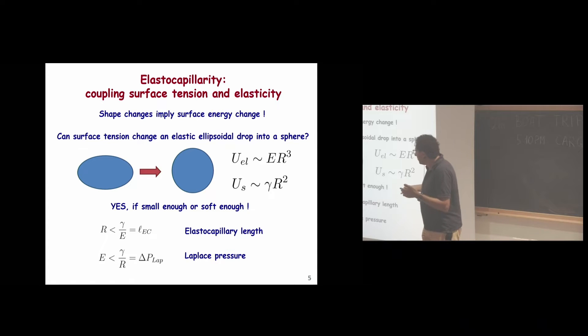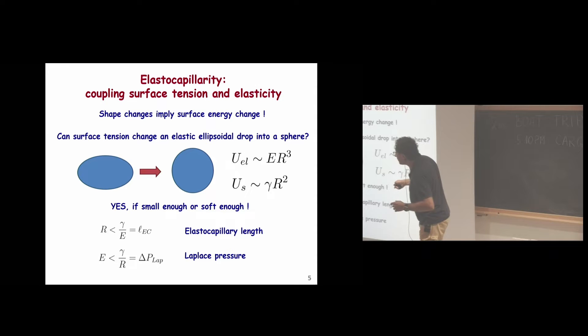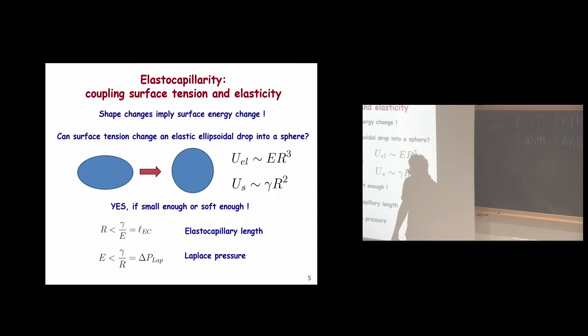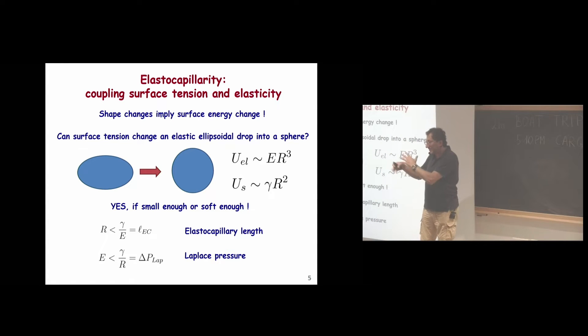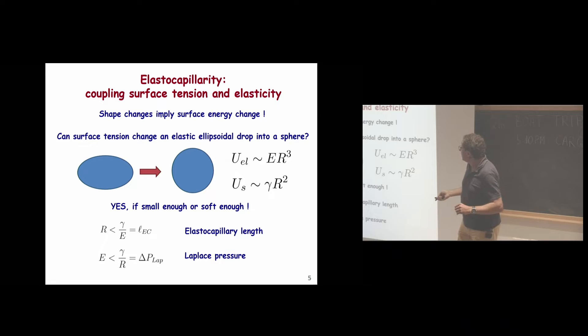You can also think in terms of Laplace pressure, as in fluids. A solid with surface tension has a pressure difference across its boundary, and if curvature varies, pressure gradients drive material to move until pressure is uniform — a sort of hydrodynamic equilibrium. Below the elastocapillary length γ/E, the object behaves like a liquid: it minimizes surface area while paying negligible elastic energy. Above that length, elasticity dominates. The elastic energy still exists but is small compared to the surface energy gain.